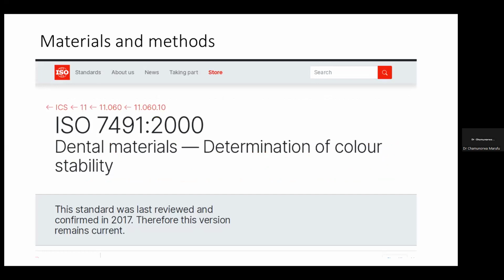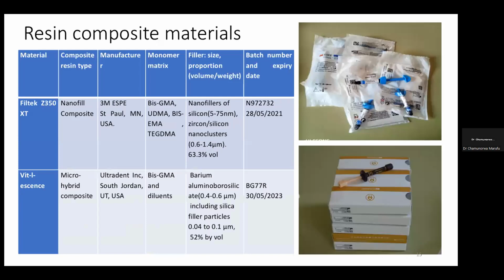we used the protocol recommended by ISO 7491, which is used in the determination of color stability of dental materials. This standard was reviewed in 2017. Apparently, they review these standards every 5 years. The only thing which we couldn't get from ISO 7491 was the sample size. So the sample size we used was determined from similar studies which have been conducted elsewhere.